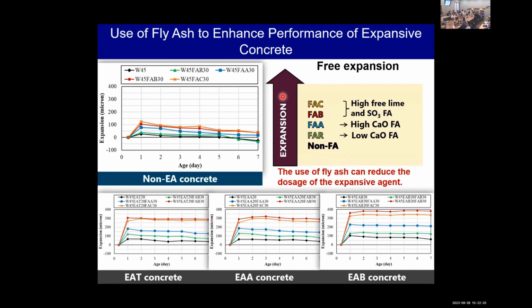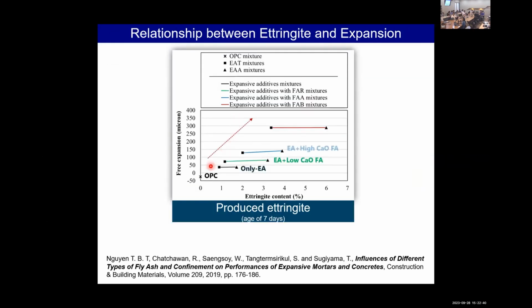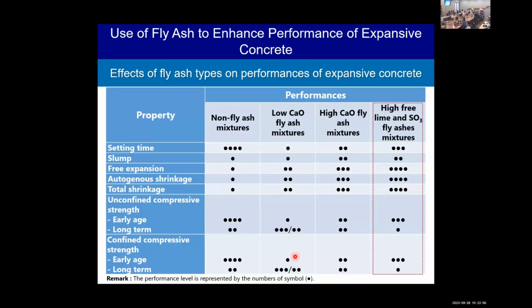High free lime and high sulfur trioxide fly ash can also be used in concrete to enhance the performance of expansive concrete. When we use fly ash, especially fly ash with high free lime and high sulfur trioxide content, the expansion of the expansive concrete is increased. The increase comes from the production of more ettringite, so the expansion can also be increased. The mechanism can be found in our previous publication.